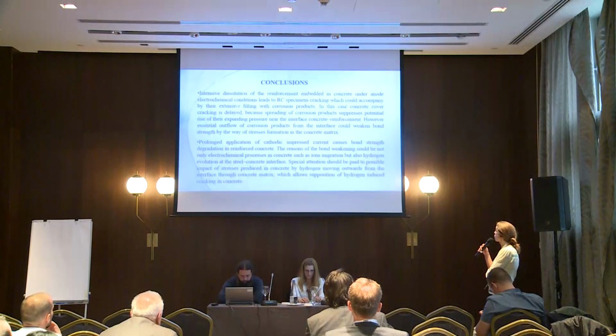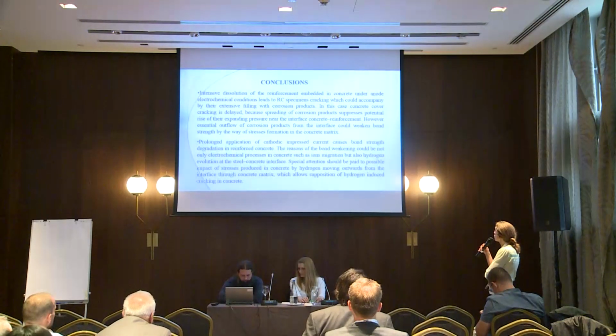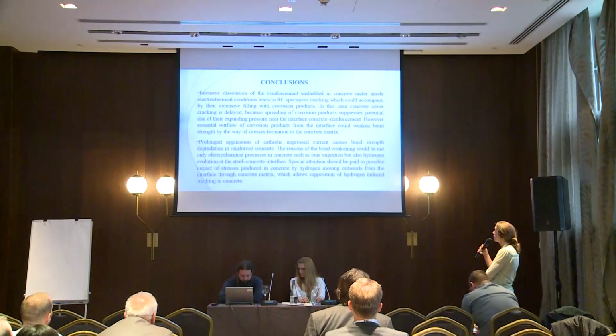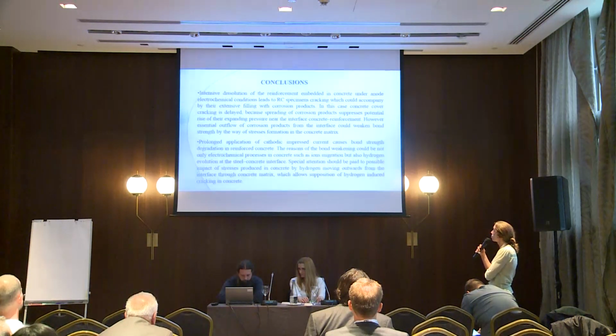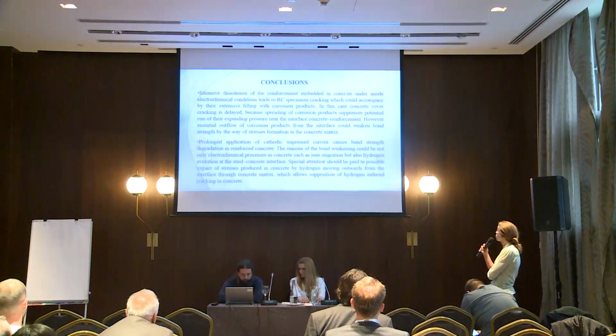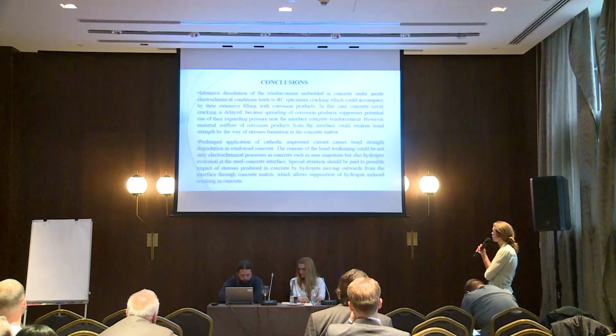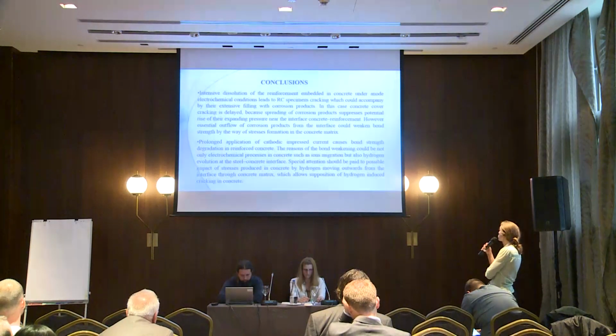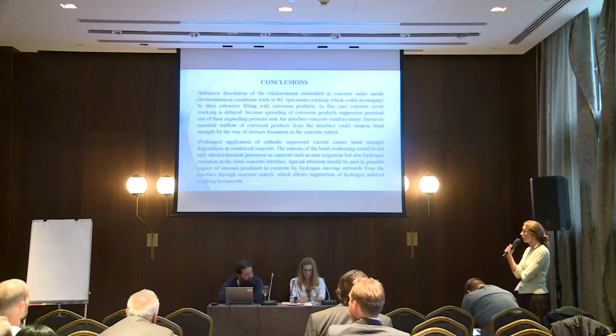The reasons for the bond weakening could be not only electrochemical processes in concrete such as ion migration, but also hydrogen evolution at the steel-concrete interface. Special attention should be paid to the possible impact of stresses produced in concrete by hydrogen moving outwards from the interface through the concrete matrix, which allows superposition of hydrogen-induced cracking in concrete.